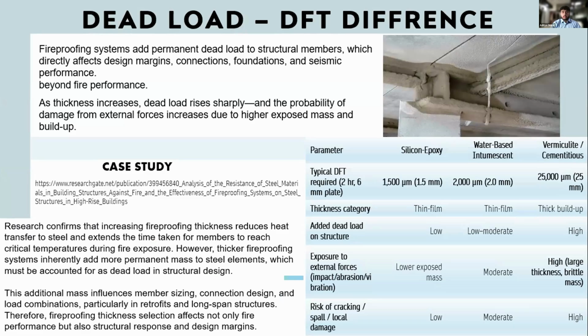Then the dead load and DFT difference. This factor is also overlooked many times. Basically, of the three types of coating, silicone epoxy requires an average DFT of 1500 microns, considering we want a protection of 2 hours on a 6 mm plate. Water-based coating will require a 2 mm thick coating to protect for 2 hours on a 6 mm plate. But vermiculite coating will need 25,000 microns, that is 25 mm, for a 6 mm plate for 2 hours of fire protection.